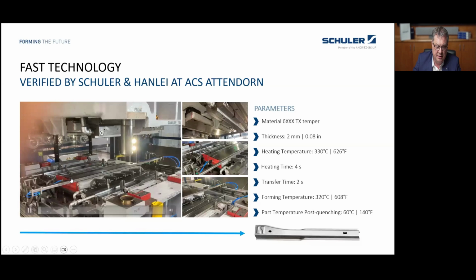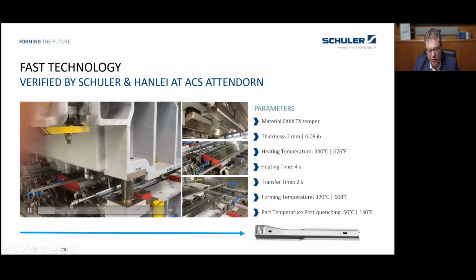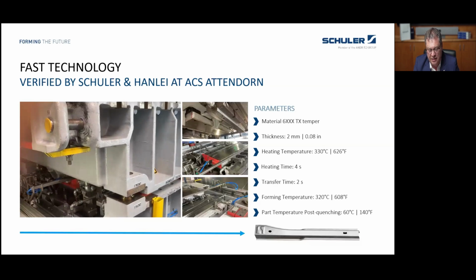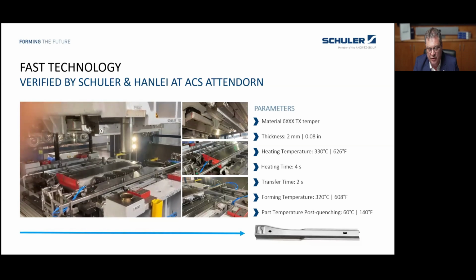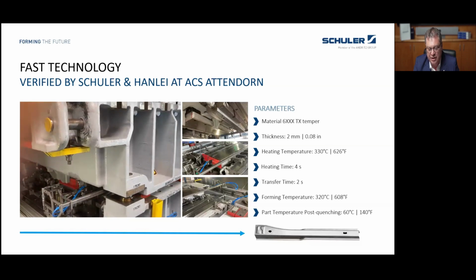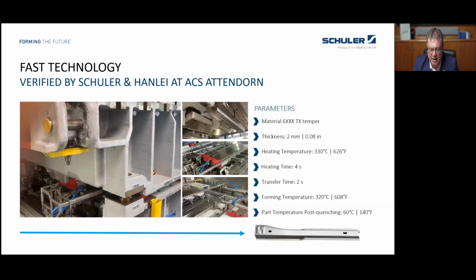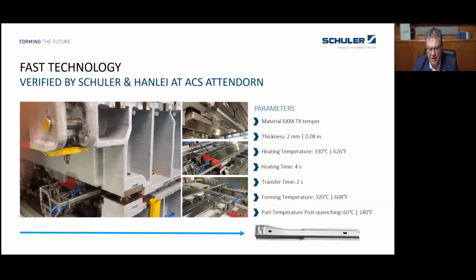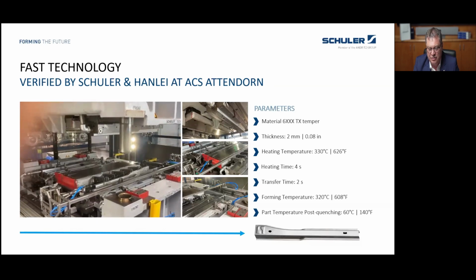So in the next picture here, we can show you the movie. The blank has been put into the heating plate manually by 2 men, and then we started the automatic process. Now we move the hot material, and now we do the forming and quenching of the part. And in this case, we cool it down very far so that we can take it out manually by hand. So this was actually our tryout setup. And during the last year, we did many trials, more than 600 parts we produced with different alloys and different setups of lubricants. So we came to a very good result for this part.